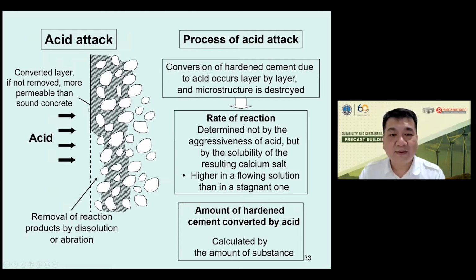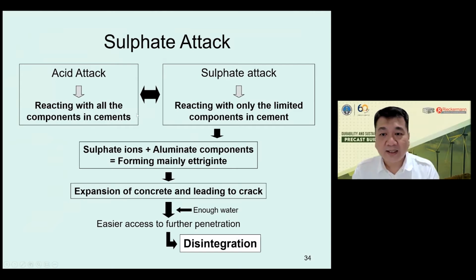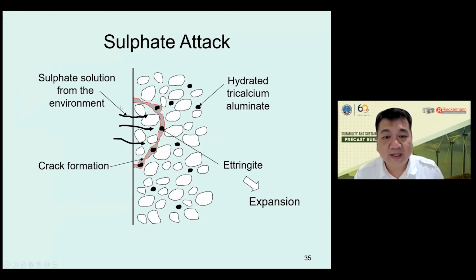Acid is exposed to our building, and then it will convert all the layers of this hydrated cement. This is the acid attack. And sulphate attack only reacts with the limited component in cement. After that, it will expand and then cause disintegration. So this is the sulphate attack. Mainly sulphate will, from the environment, enter the concrete and then react with the calcium aluminate component, the black one. And then after that, it will expand and cause some cracks in the concrete.